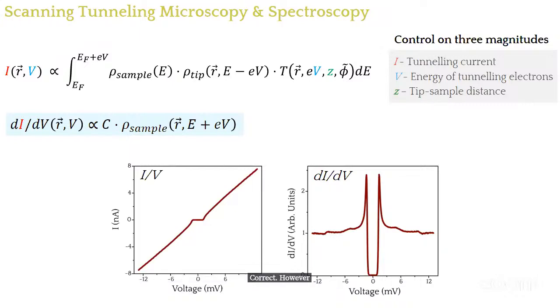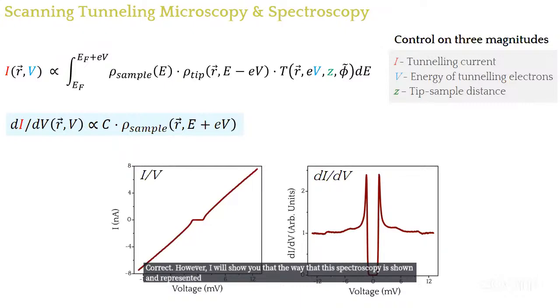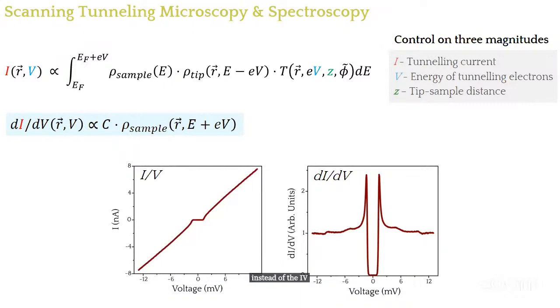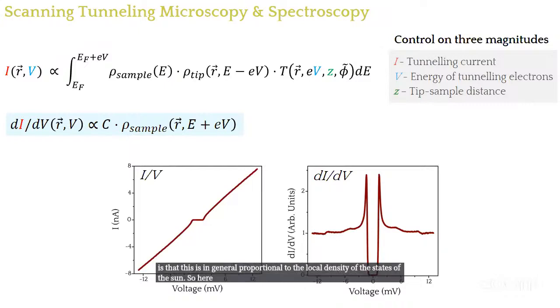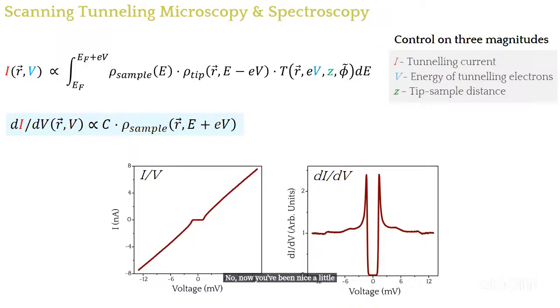However, the way this spectroscopy is usually shown is the dI/dV instead of the I-V. The reason is that under certain assumptions, this value, called the differential conductance, can be considered just proportional to the local density of states of the sample that you are studying. So this is the way these curves are normally represented. What I'm showing here is the superconducting gap of lead, I think. No, niobium diselenide. And zero bias represents the Fermi level.